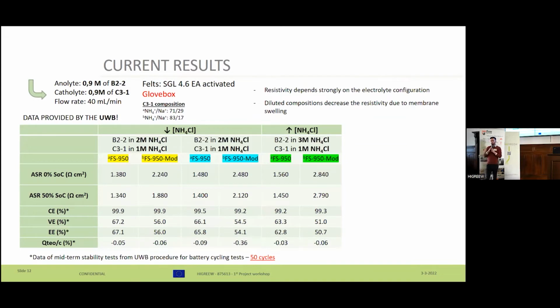And also here in this slide, I collected some interesting data, which was provided by the University of West Bohemia, that I would like to comment and share with you. So first of all, I would like to point out that membrane is a sensitive material, and the different properties that you can find in these materials strongly depend on the electrolyte configuration, because these membranes swell and have a certain level of hydration, and depending on this level of hydration, the ion conductivity will be different. So in general trends, in diluted compositions compared to the concentrated ones, the resistivity was decreased, and this is because the membrane swells and there are different osmotic pressures between the outside of the membrane and the inside.